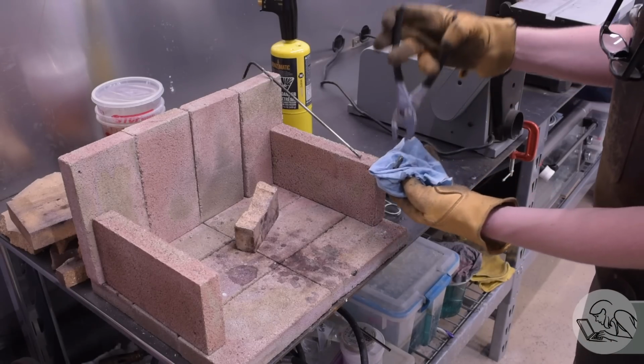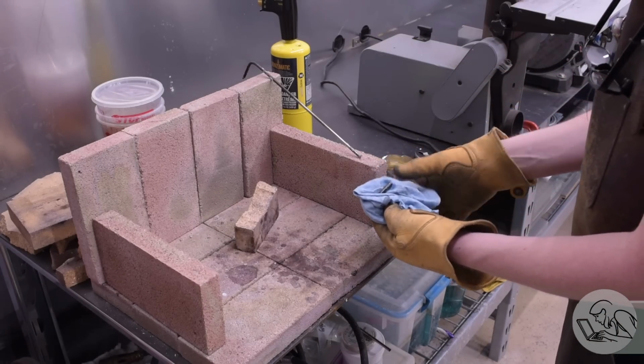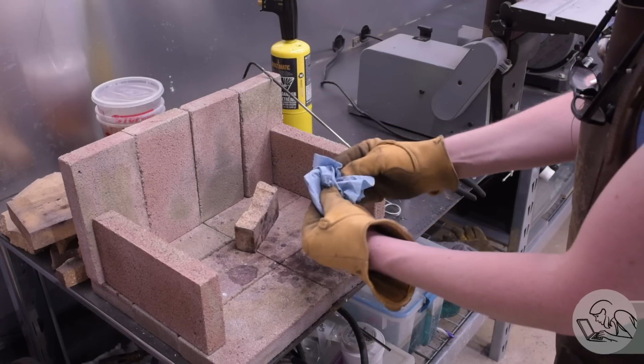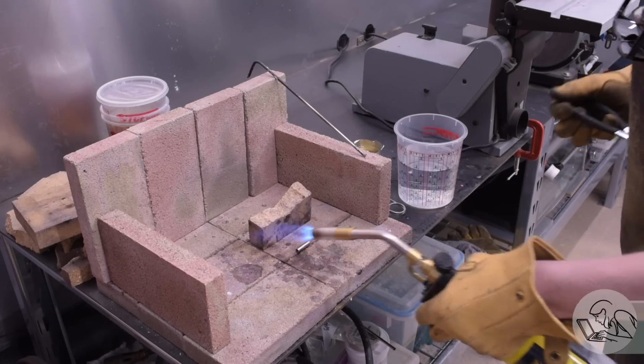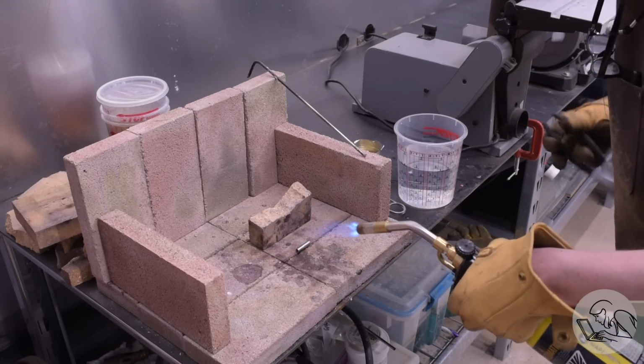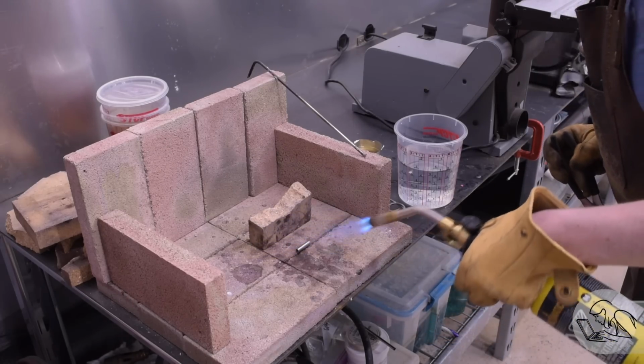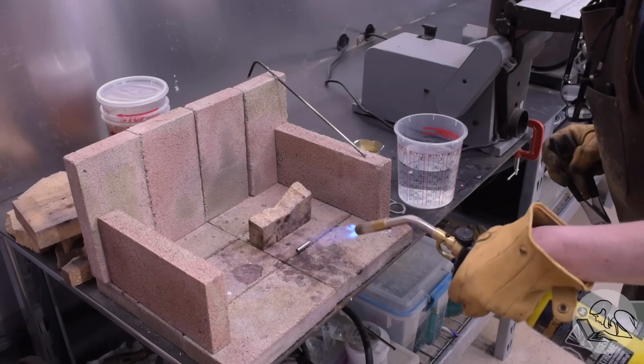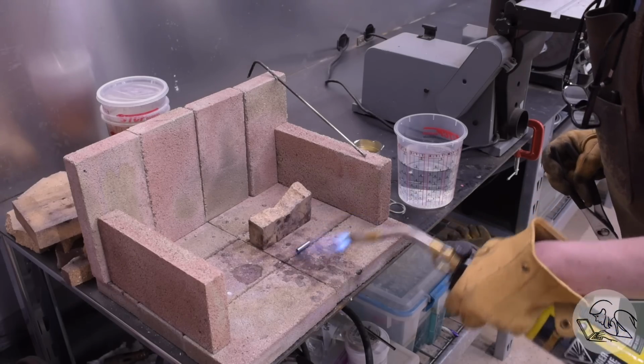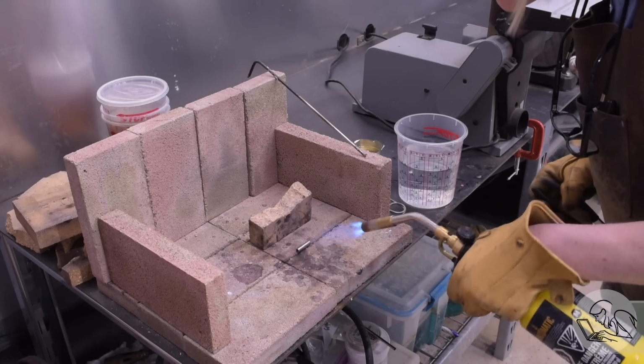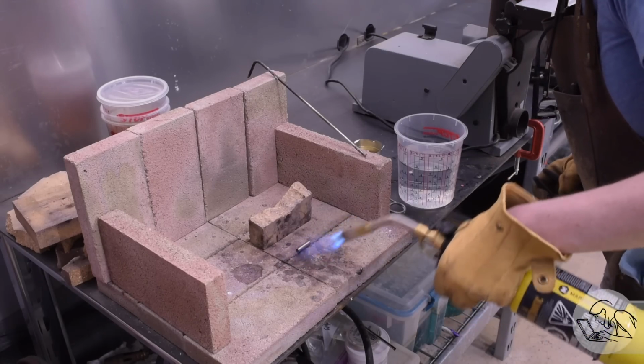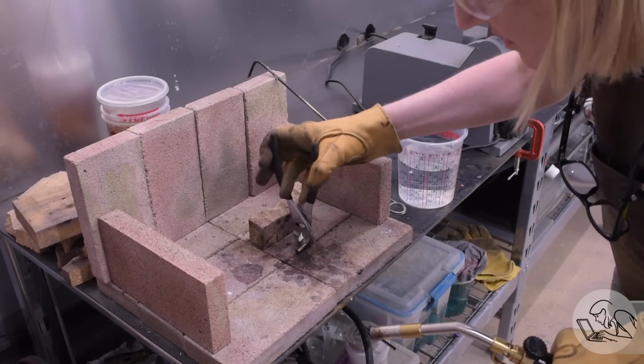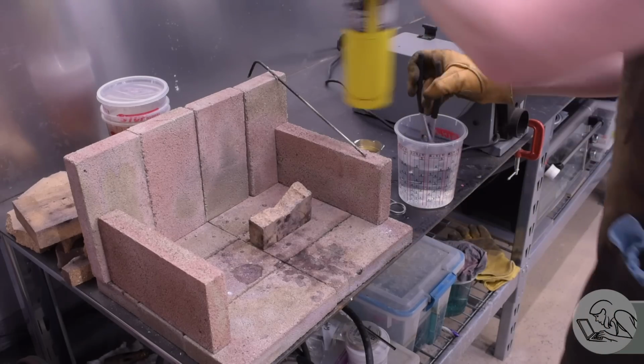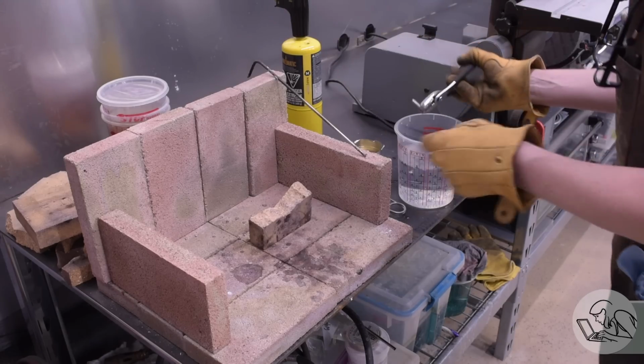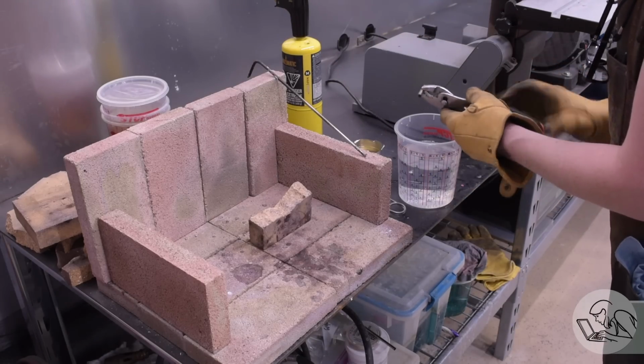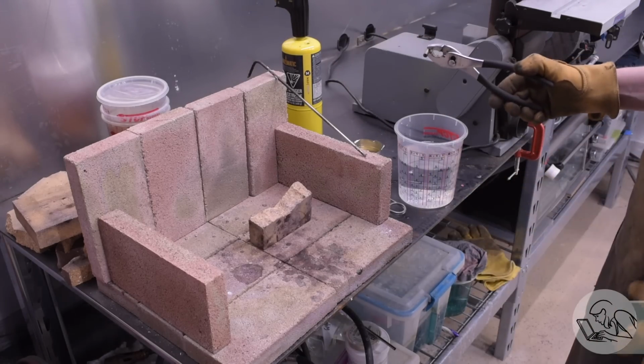Once that's cooled down, then I clean the soot off with the Scotch-Brite wheel, and it's now extremely hard, too hard in fact. Now it's brittle, so then we temper it. I did a whole video on heat treating in the home shop with a simple torch like this if you want to know all the details, but at this point now I feather the torch on it very, very gradually, keeping a very close eye on it. As soon as I see a little bit of yellow start to appear on that surface, then I grab it and I dunk it in water. And the water here is not a quench because we haven't heated it up to that cherry red temperature. The water here is just stopping the heat so that the temper stops exactly where I want it.